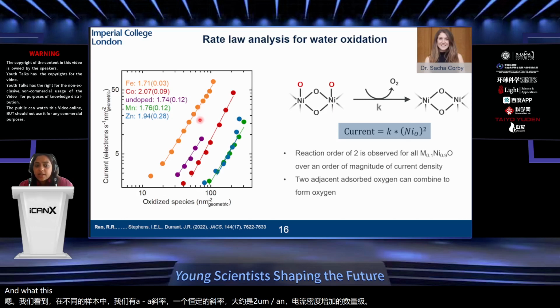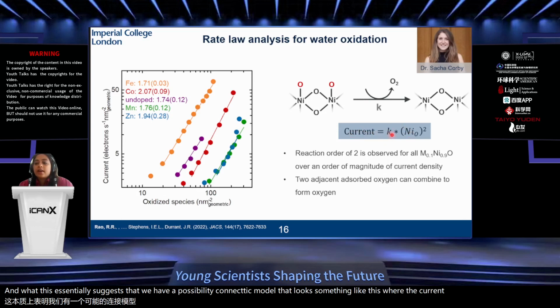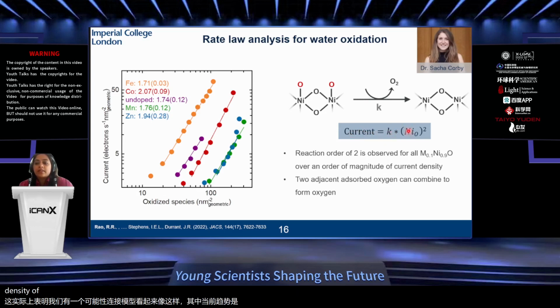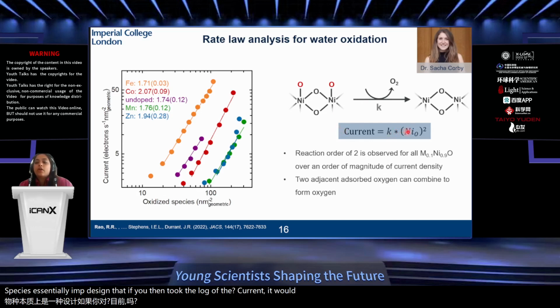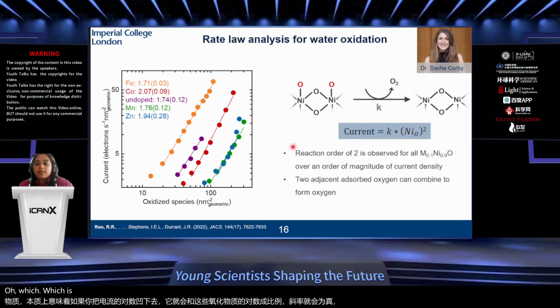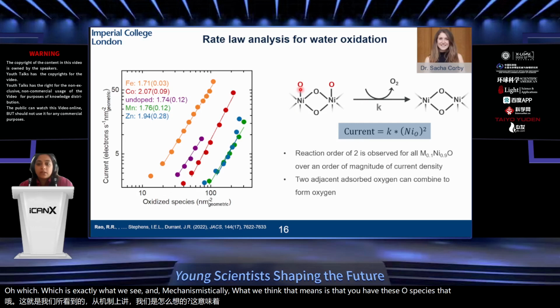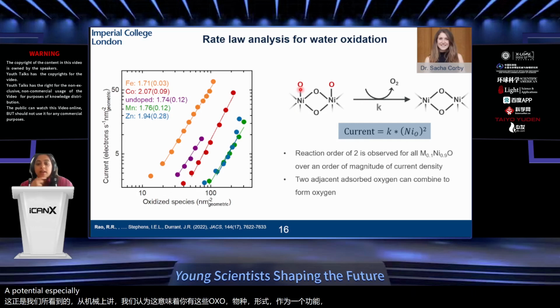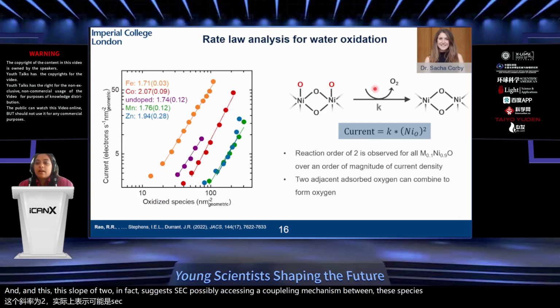What this essentially suggests is a possible kinetic model where the current trends as a square of the density of these oxidized species, implying that if you took the log of the current, it would scale with the log of these oxidized species, and the slope would be 2, which is exactly what we see. Mechanistically, we think you have these oxo species that form as a function of potential, especially at water oxidizing conditions, which is what we probe with optical spectroscopy. And this slope of 2 suggests that you're possibly accessing a coupling mechanism between these species to evolve oxygen.